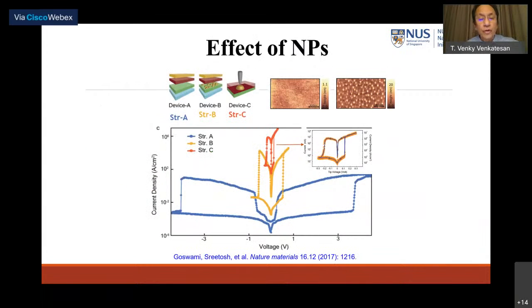We can also look at the effect of field enhancement and what it does. For example, we make 3 different types of devices. In device A, the bottom electrode is large area, and the top electrode is also large area. So there are 2 flat electrodes with the molecules in between. What do you see? The current density barely gets to about 10 to the 2 amp per centimeter squared, and the switch on voltage is around 4 volts or so.